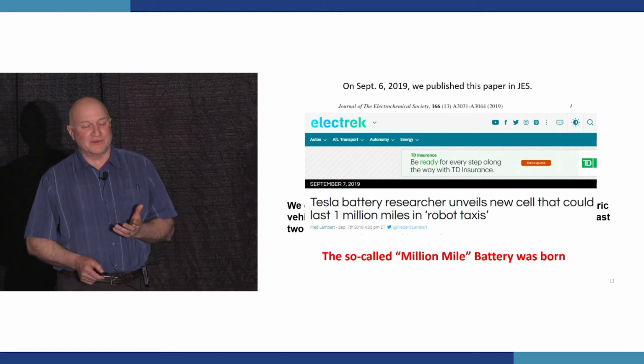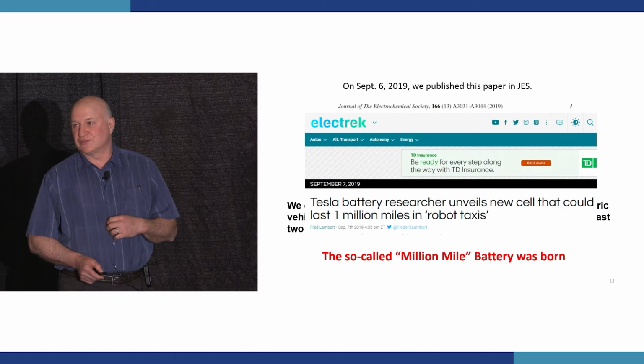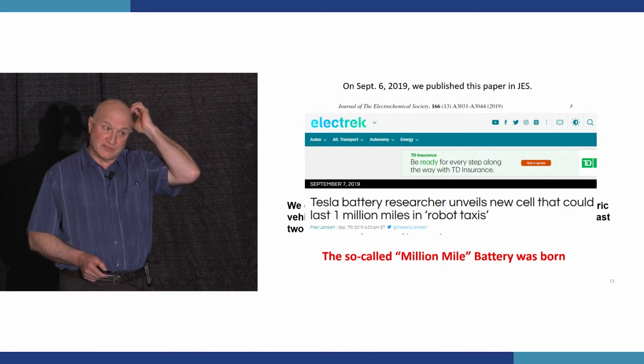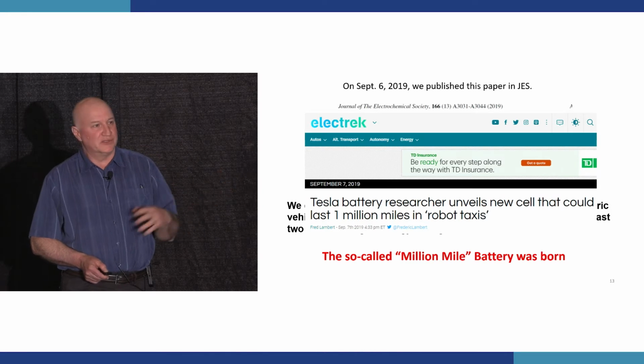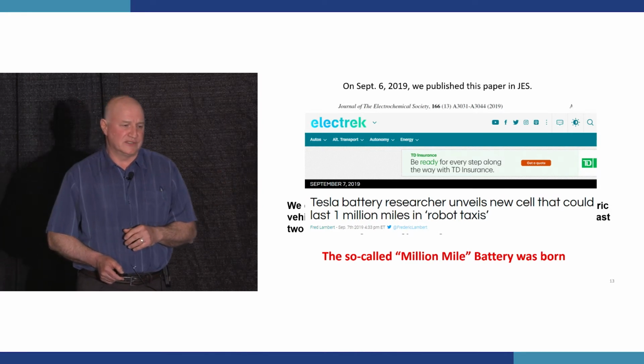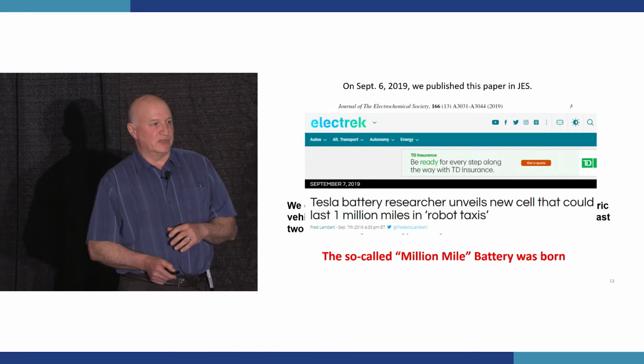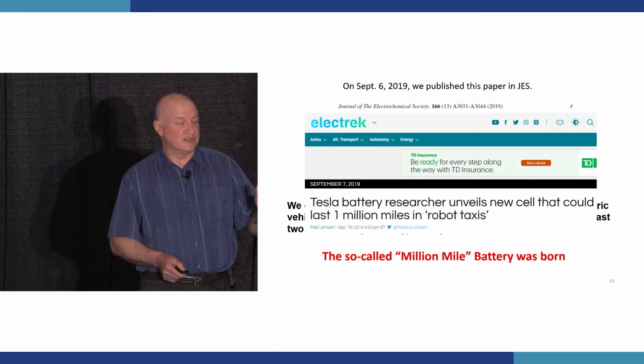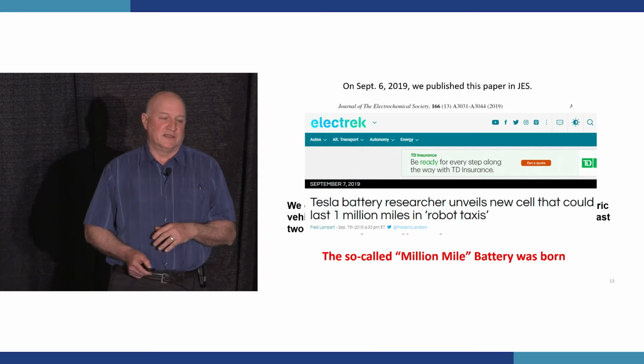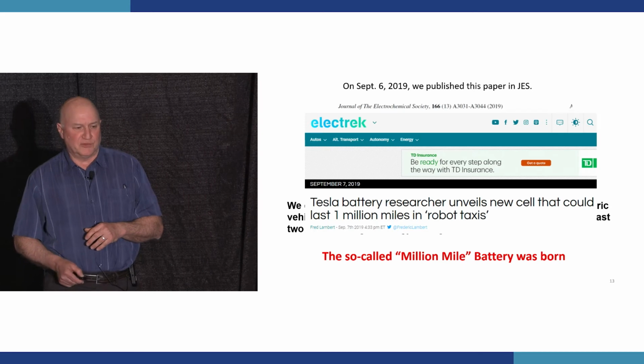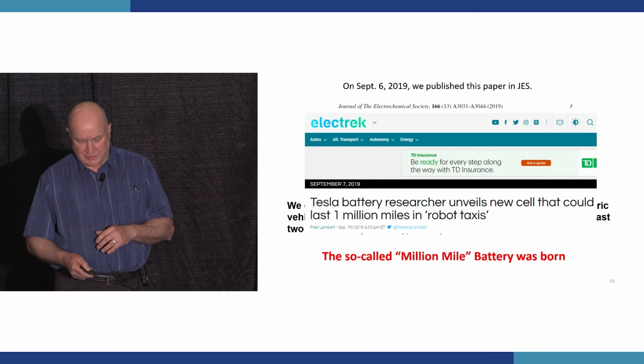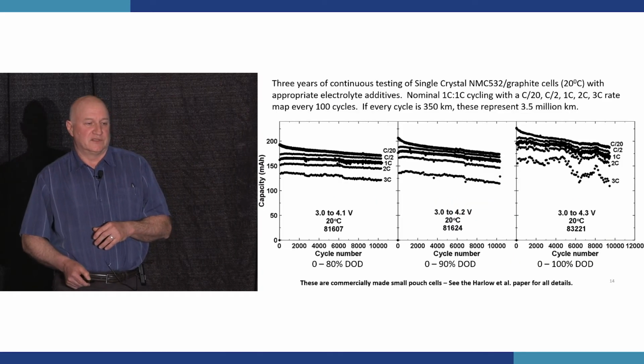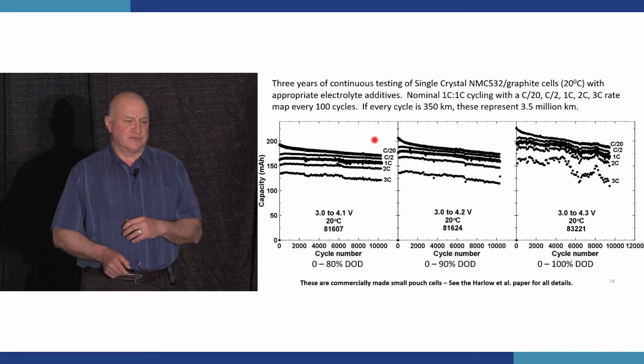So in this paper, we showed testing results for several years of testing where cells accumulated 3,000 or 4,000 cycles. And many of the cells in that paper, we left them on testing from 2019 till the present. And they've racked up a lot more charge-discharge cycles in the meantime. So here are 3 years of testing results on these batteries.